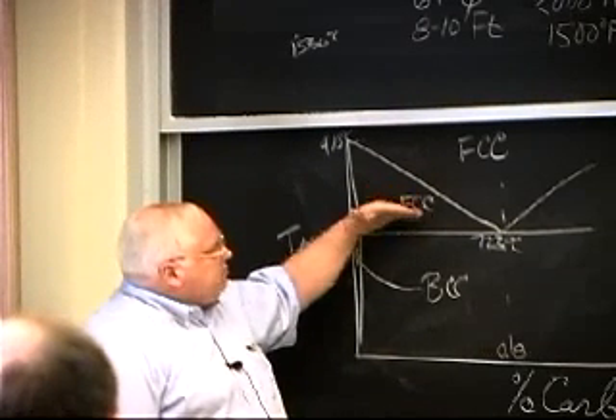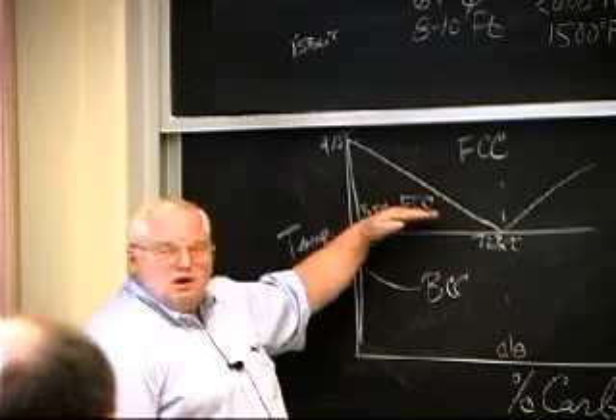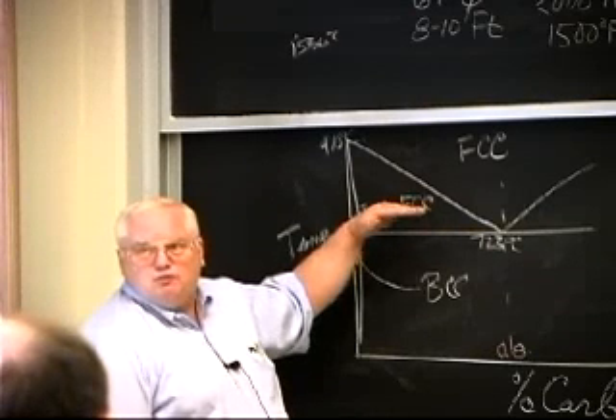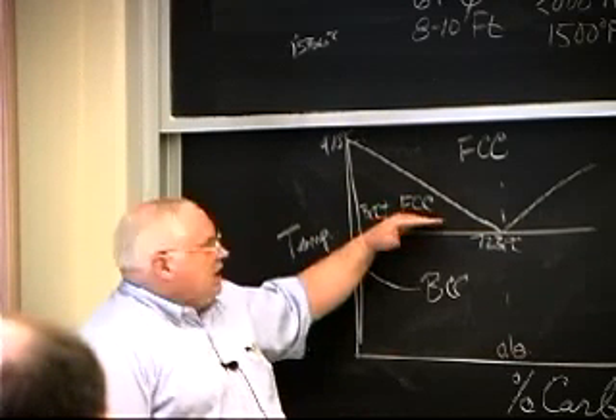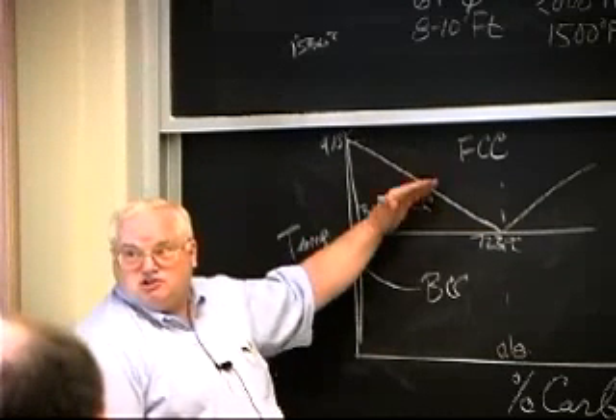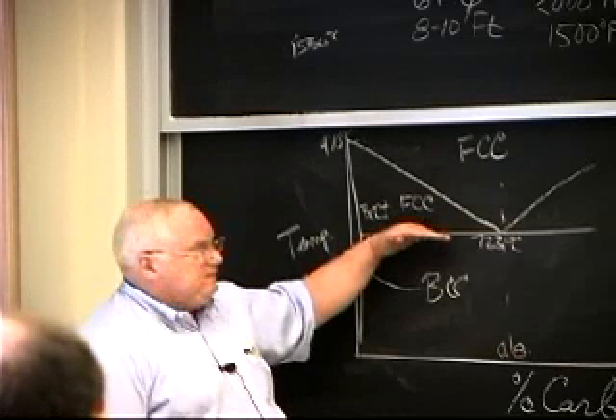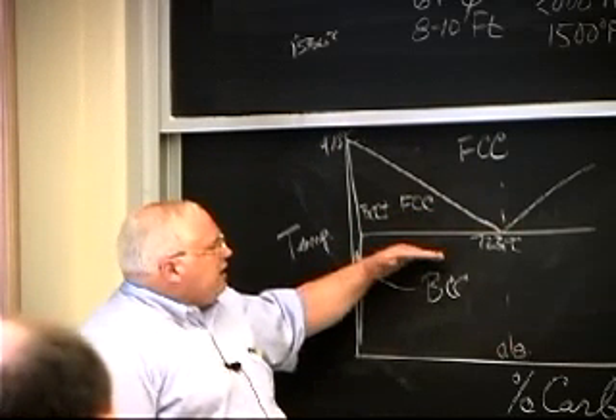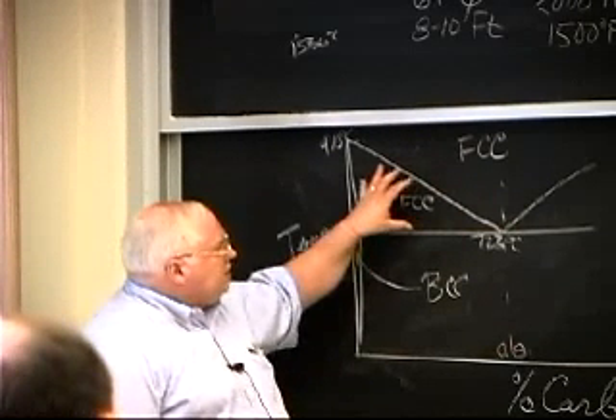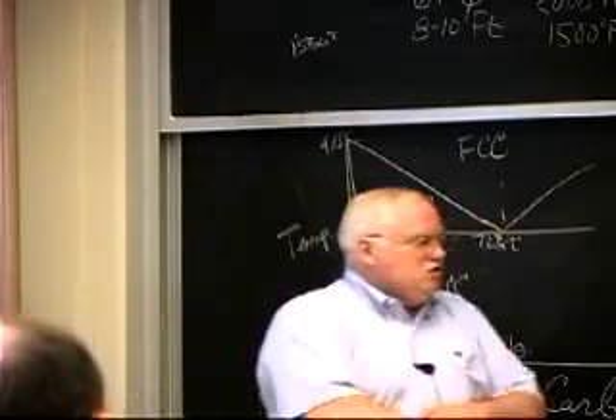They had enough power in their rolling mill, they could roll and deform the plate at temperatures down as low as this, because the steel is starting to get stronger down here, okay? You don't want to roll down here, but you really want to roll in this, what we call two-phase region, because you can get these very fine grain sizes. That was called control rolling.